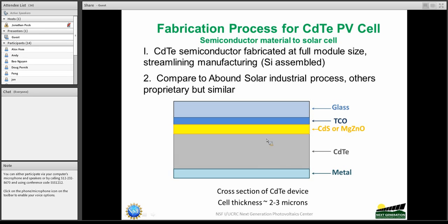Then cadmium telluride is the absorber where the sunlight comes in and creates electron-hole pairs, and there is a metal at the back, and between the metal and the transparent conducting oxide is where you generate the voltage and current. And the cell thickness from here to here is about 2 to 3 microns. So it's a fairly small thickness of material compared to the silicon process.